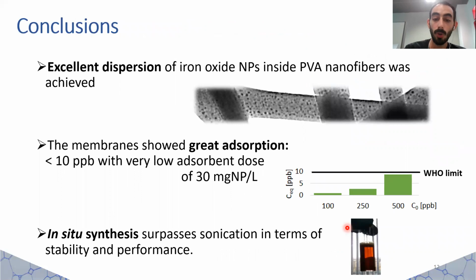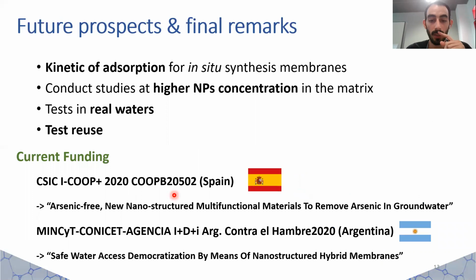So we conclude that this method allows an excellent dispersion of nanoadsorbents inside PVA nanofibers. In turn, this favors the high efficiency observed in adsorption experiments, reaching less than 10 micrograms per liter with initial concentrations of up to 500 micrograms per liter. And in situ synthesis surpasses suspension with tip sonication in terms of magnetite content and solution stability. We will study the kinetics of adsorption for the in situ approach, test higher nanoparticle concentrations in the matrix, test reuse of the membranes, and performance in real waters.